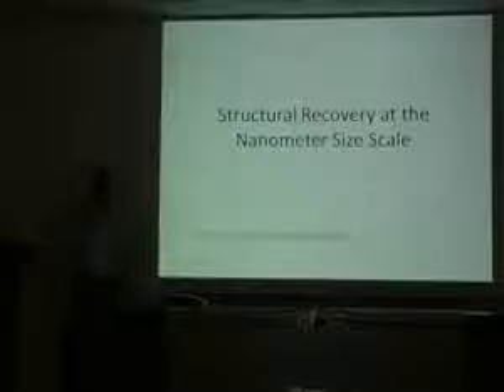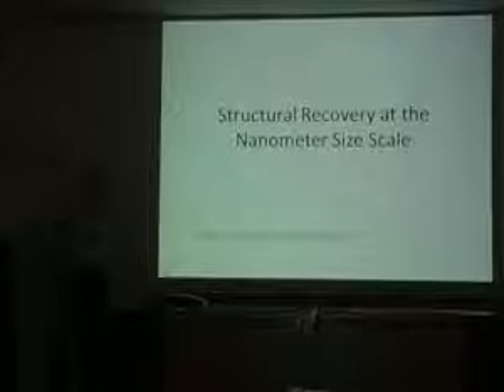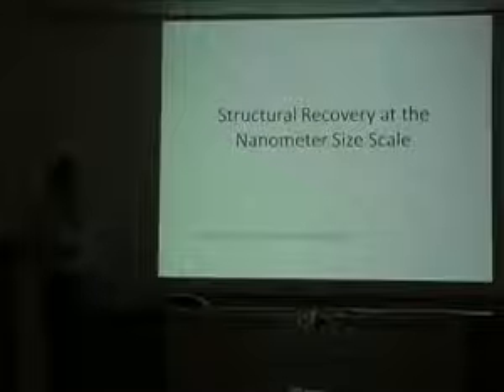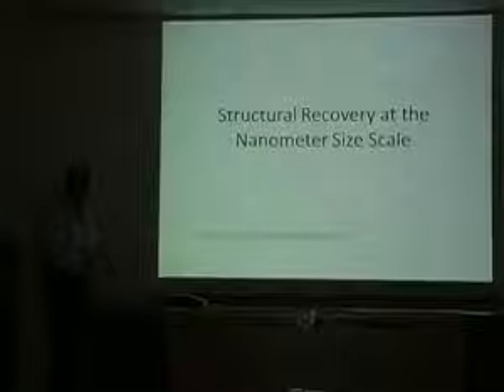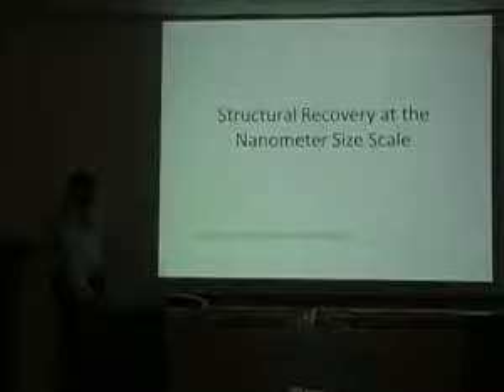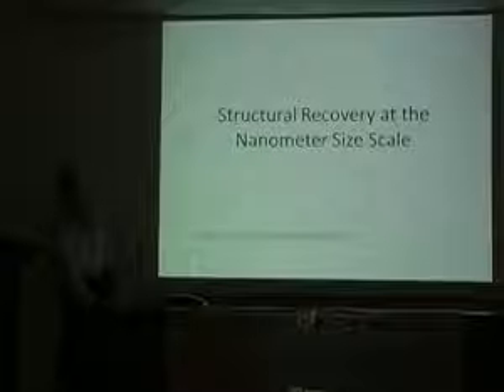Okay, so the last thing I want to talk about is what's happening at the nanoscale. Okay, so structural recovery at the nanometer size scale is something that people are interested in, TG at the nanoscale, what happens. And what we had done was we took orthoterphenyl, it's a sort of ubiquitous glass former. We imbibed it into these controlled pore glass beads, which have pores, well, we went all the way down to 4 nanometers, but 11, 25, and 50 nanometers about. And here's what we see.